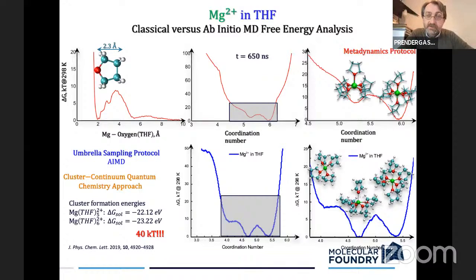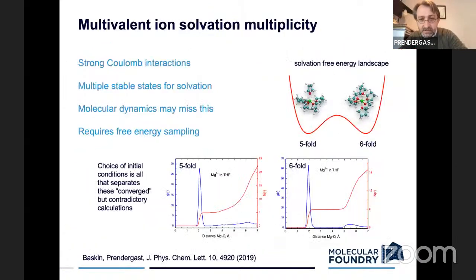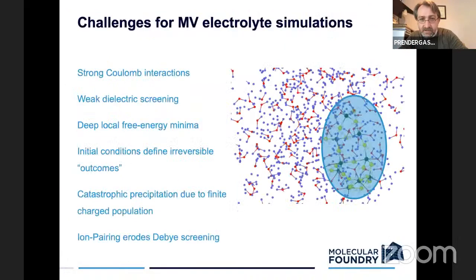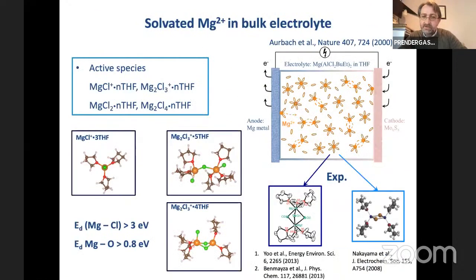So first of all, I didn't show this, but the initial confusion around these different coordinations in solution was based on two different X-ray experiments. They did talk about local coordination, so they were XAFS experiments that should tell you about coordination number. Both experiments came to different conclusions about what the coordination number was. So that's maybe a hint that there might be some differences out there in the literature that would imply that there are different populations.